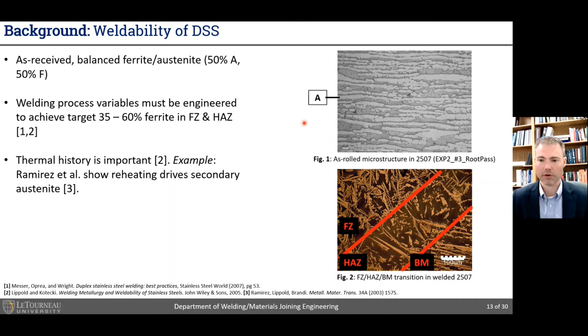Now, the welding process variables must all be engineered to achieve this 35 to 60% ferrite in the fusion zone and the heat affected zone. Now, of course, this will depend in great detail upon the composition of the material, which will drive the kinetics of the phases that form, and the welding process conditions, such as heat input, that control the cooling rates. So all these details must be considered in order to achieve the target microstructures. Thermal history is known to be important, as I've already mentioned, about the potential to drive secondary austenite formation.